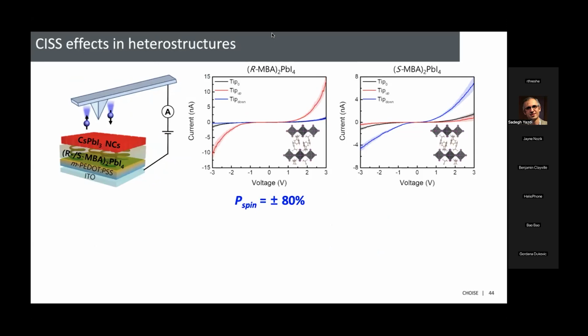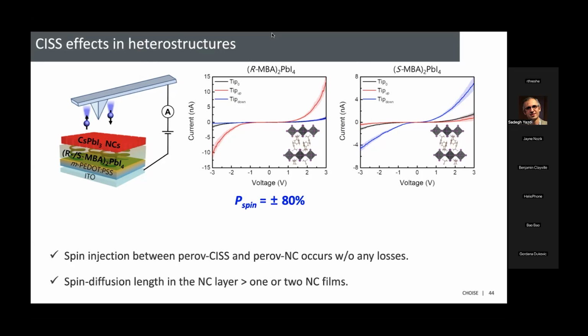Okay, so we can do this in very solution deposited systems. We have our chiral perovskite, we have a non-chiral perovskite as well. We can measure the spin across this interface, and we also get really high spin polarization across the interface. So that means already that our spin injection over here is already really good. And that's because it's a semiconductor junction, not a semiconductor-metal junction, and so you don't have this conductivity mismatch problem.